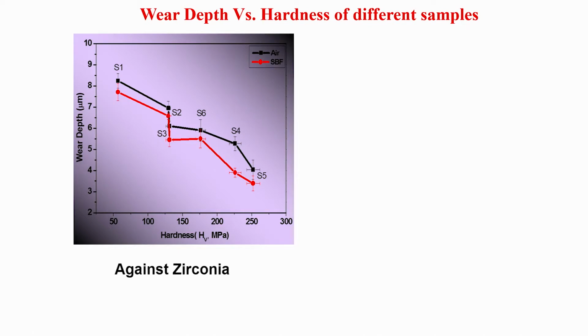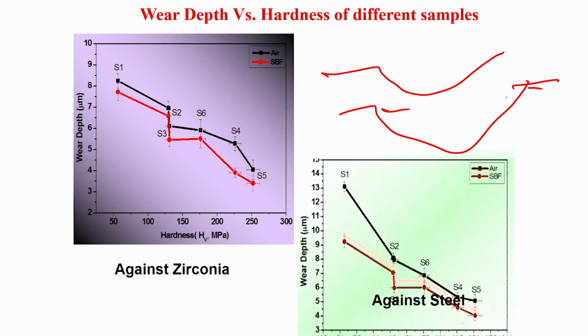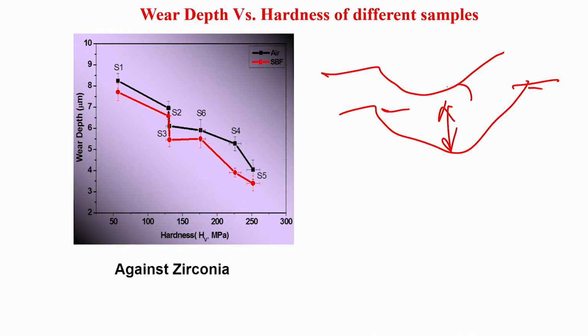Now the severity of wear is not only measured by the wear rate, but also by the wear depth. Here you see how this wear depth decreases with hardness of the materials. Wear depth here means the maximum wear depth - if you take the profile and line it up, this is the maximum reported along the y axis. Essentially, wear depth is less than 10 microns, that is the first observation. Second, although there is an apparent decrease - not apparent, there is a clear decrease - in wear depth with the flat hardness of the material, the qualitative trend is almost similar to that of the variation of wear rate against hardness.